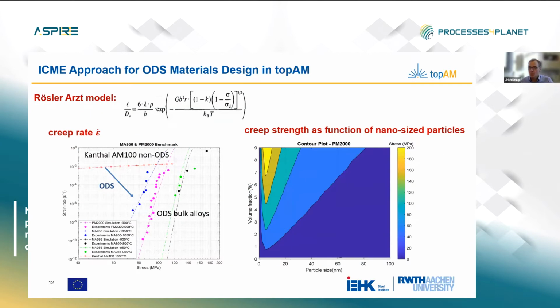Here you see a model that we are using to predict the creep rate, and it shows that the model works quite well. So for ODS bulk alloys, that is the non-ODS AM100 that we are going to optimize by ODS, so that we have a substantial decrease of the creep rate.